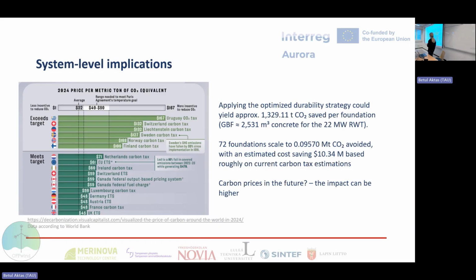So to look at the whole system of the offshore structures, if we consider concrete, it's actually not such a small part, and it can give us substantial savings if we look at the numbers here that are calculated for the case that Bjørnar showed earlier, and taking into account our LCA calculation.